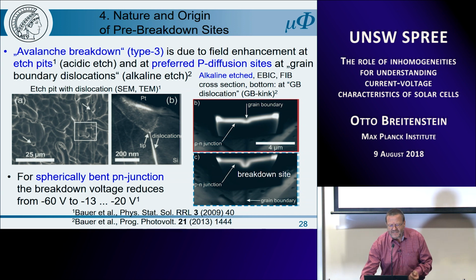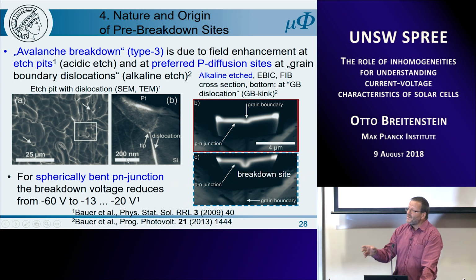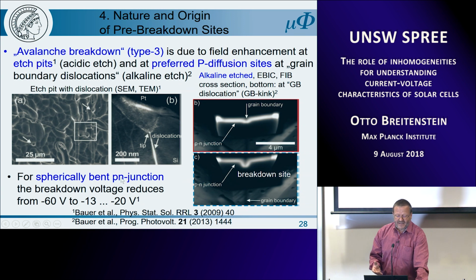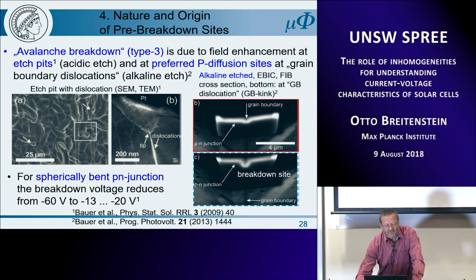And in these etch pits, it looks like this, and this is 200 nanometer, and the depth of the pn-junction is 300 nanometer, a little more. So we expect here the edge of the pn-junction to be spherically bent. And there's old literature that has calculated that a spherically bent pn-junction with 300 nanometer diameter just leads to a reduction of the breakdown voltage from minus 60 to minus 13 volts.